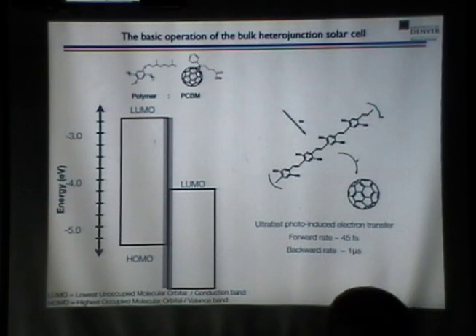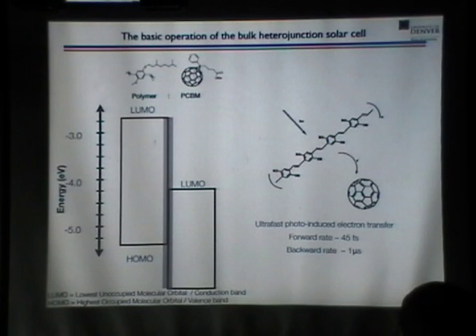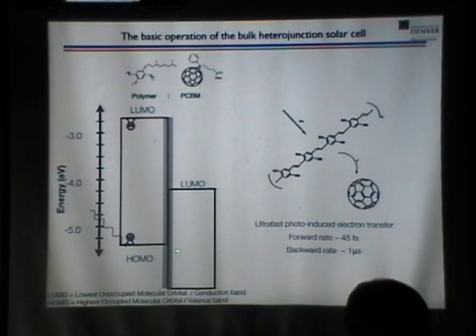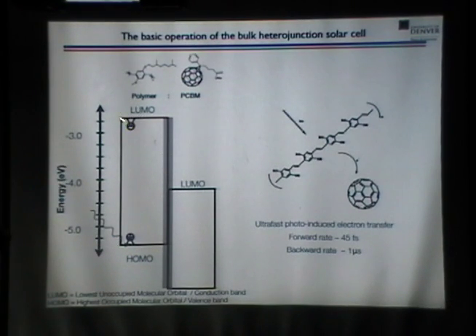Okay. So to go into slightly more detail about the operation of the device. We have our polymer and our fullerene. We can draw a band structure for each one, a HOMO level, a LUMO level. Those are electronic bands. So what happens is we come in with a photon to excite this exciton. Now the exciton can be envisioned by a hole and electron that are coulombically bound. And that means that the band structure dips in a little bit there. So there's a coulombic attraction, and so the energy difference between this positive polaron, we'll call it a polaron, and this negative polaron, is a little bit different than just the single particle energy that would be there without the opposing species. So these two are bound a little bit, and that energy of binding is called the exciton binding energy. So that keeps the two stuck together.